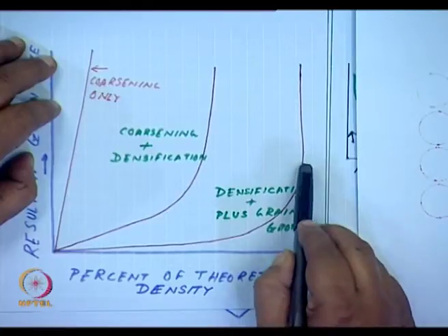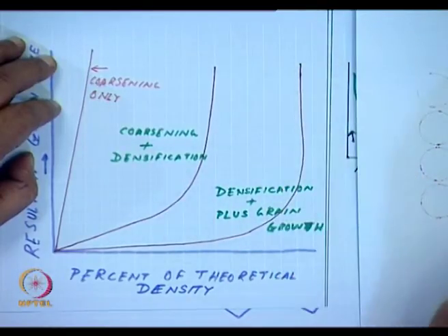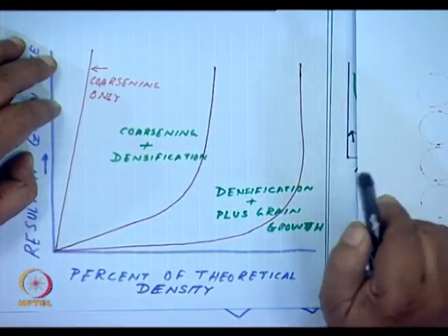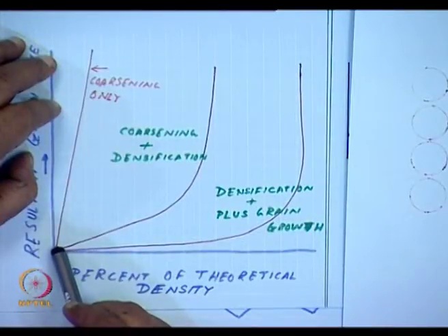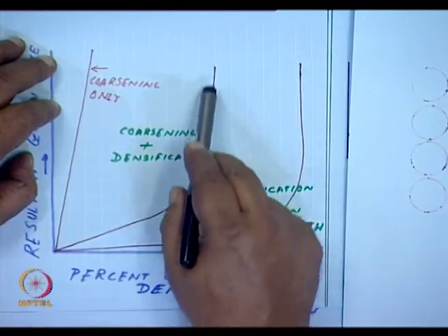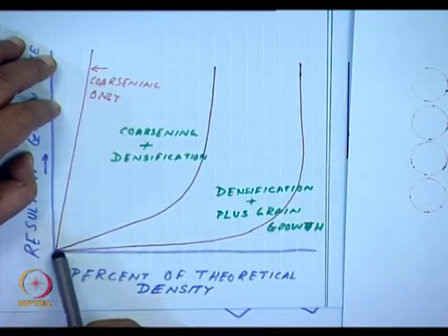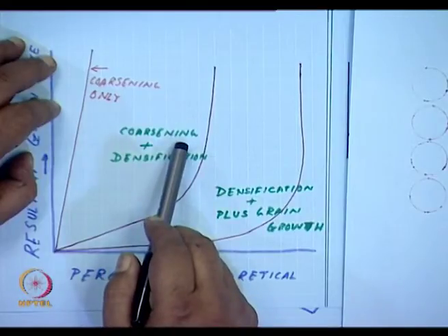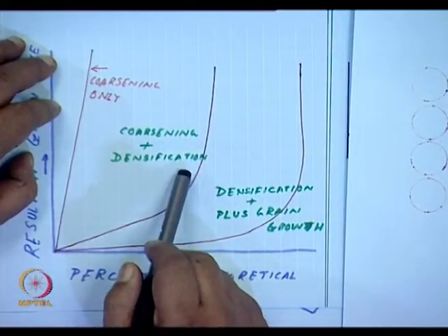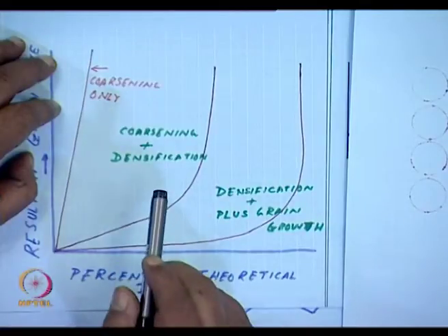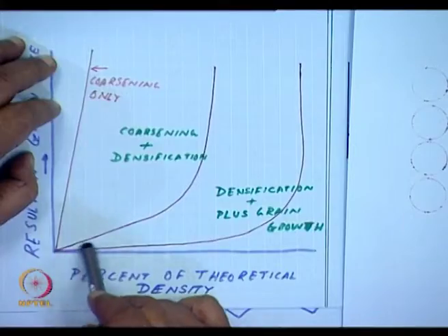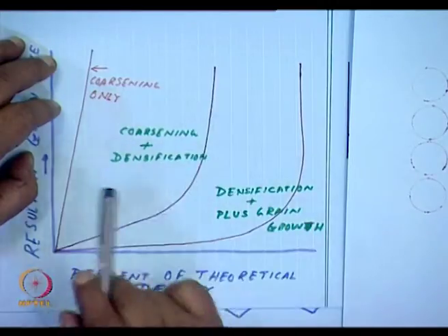This is what we ideally wish to achieve in ceramic processing. However, in most cases we are hindered by the fact that what we have is coarsening and densification. In most normal cases, we have grains getting coarsened and densified. I had showed you a graph earlier today where you had seen large size grains mixed with fine grains. That is due to this coarsening and densification.